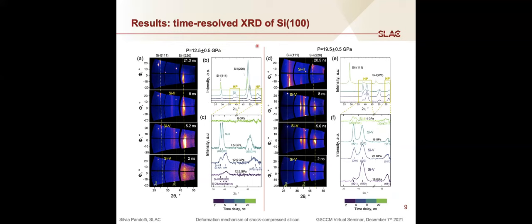I'm showing two different time series obtained for different peak compression pressures of 12.5 and 19.5 gigapascal. And so what you're seeing, from the bottom of the image to the top, are the different X-ray diffraction images, which have been projected along the diffraction and the azimuthal angle. And on the side, we can also see the integrated 1D diffraction pattern in its whole extension, and also with a zoomed-in panel to better see the signal from the high pressure phases.